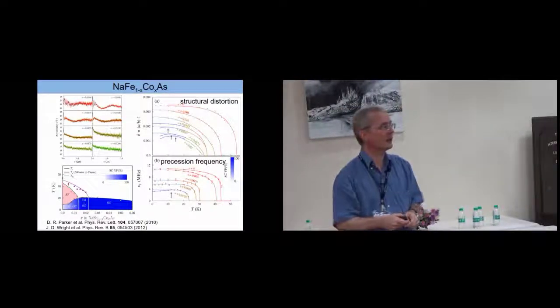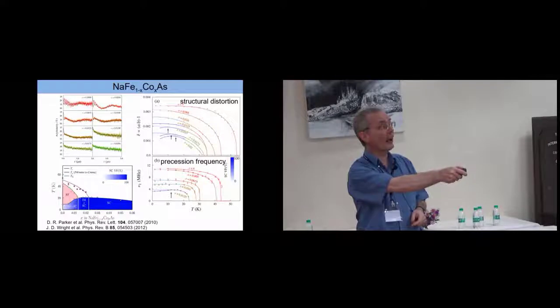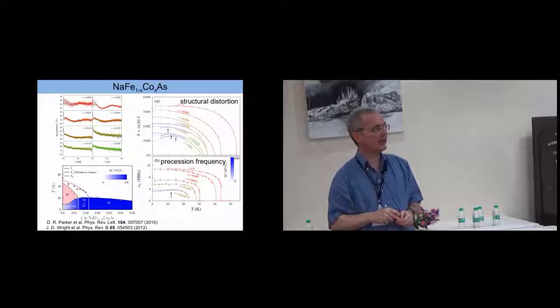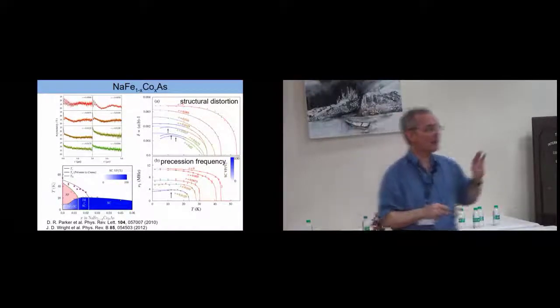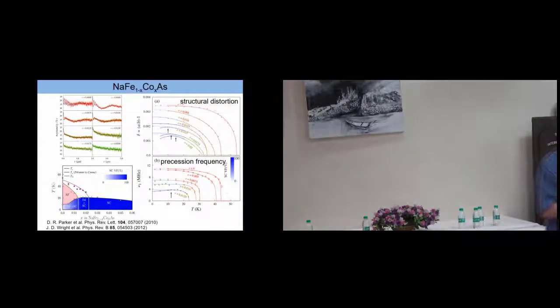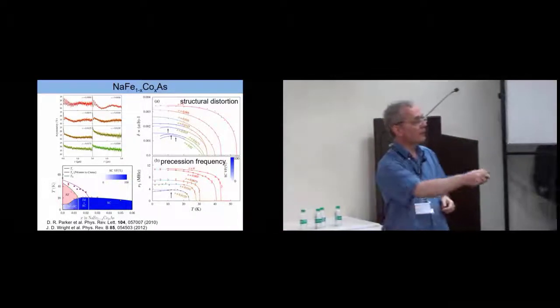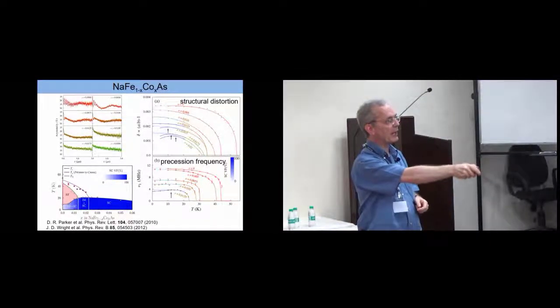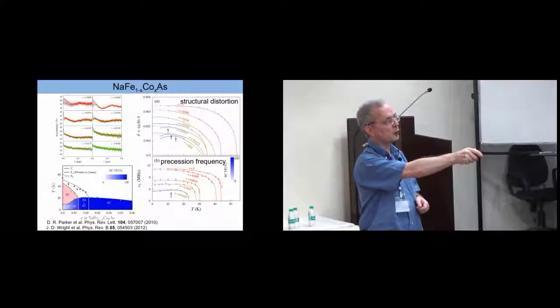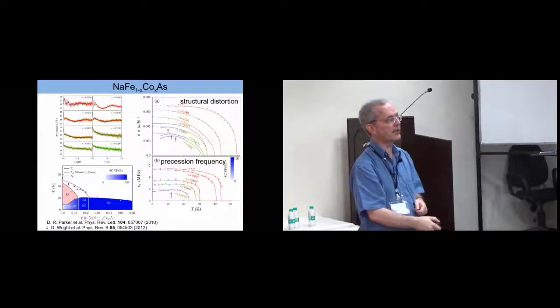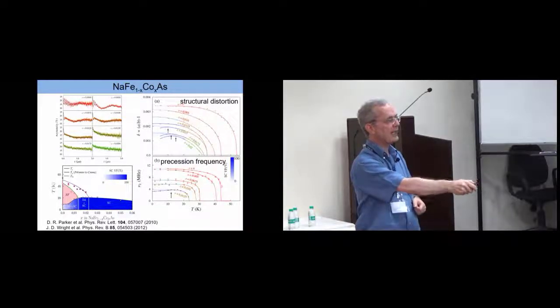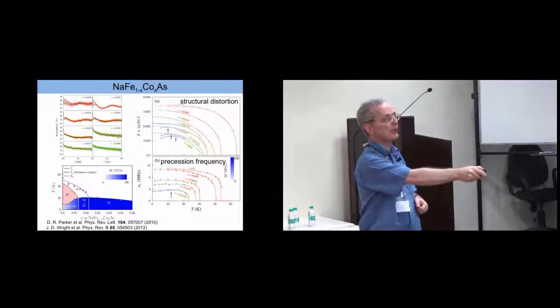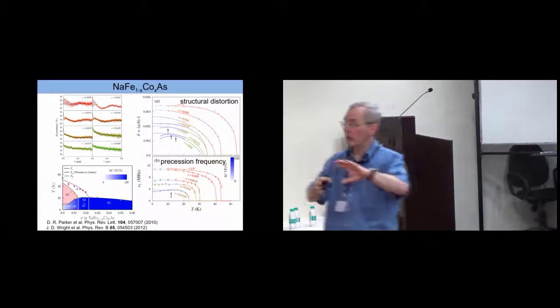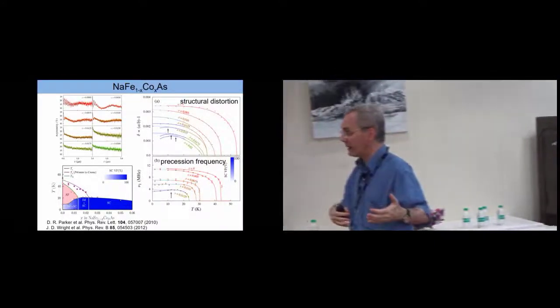And maybe one final example. This is a superconductor, sodium iron arsenide doped with cobalt. It has a rather complicated phase transition. I just wanted to point out here that the magnetism can be studied very nicely with μSR. In this right-hand panel, you see the structural distortion in these materials that go from orthorhombic to tetragonal. And you also see the magnetism as measured by μSR. You can see that the structural transition occurs at a higher temperature than the magnetism. It's thought that the structural transition facilitates the magnetism.